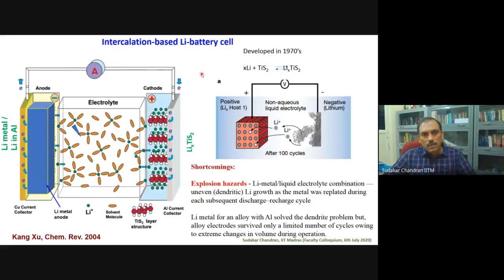One of the important things with this particular cell design that Stanley Whittingham came up with is that it exhibited 2.5 volt, which is very good. The cyclability was good, but then it had problems. The shortcomings are that in this device, when lithium goes back and forth, it doesn't get uniformly coated every time. Instead, it grows very unevenly on the lithium surface, and therefore dendrite-like growths happen. As one microscopic picture shows, the dendrites grow, and eventually they touch the cathode and internally short circuit the battery. Therefore, the battery catches fire, and with electrolytes which can easily catch fire, it explodes, and that was a problem.